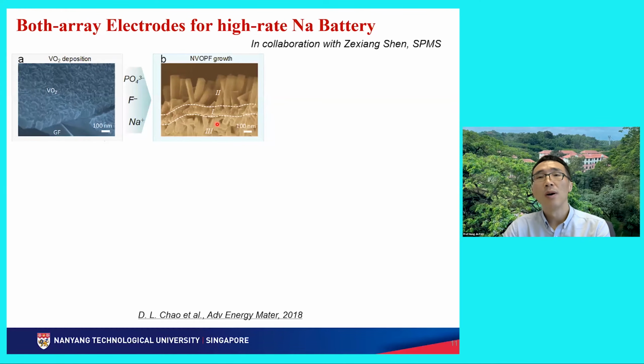But before us, no one had realized the fabrication of an array structure, meaning a direct growth of NVOPF material on the current collectors. We always use a solid-state reaction mechanism to get powders and then mix them with carbon additives and polymer glues. So in these papers, we first grow vanadium oxide array structures on a three-dimensional graphite foam. We use this as the anode material. Then we take another reaction step to convert this vanadium oxide to the typical sodium vanadium phosphate material. This is the cathode material.